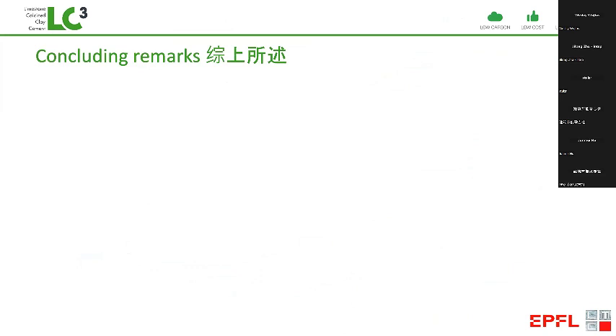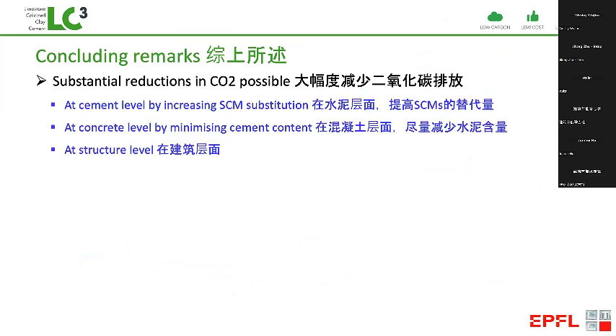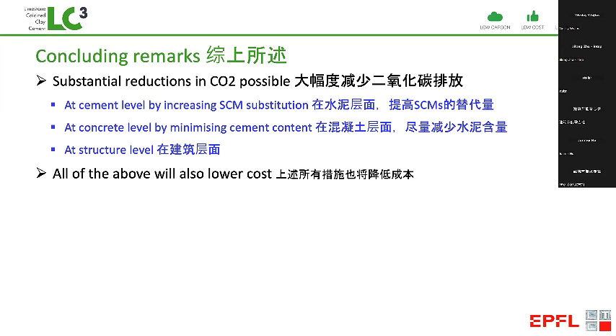So to conclude, I hope I've managed to convince you that substantial reductions in CO2 associated with cement-based materials are possible. We must work at the cement level by increasing the substitution of SCMs. We must work at the concrete level by minimizing cement contents. And we must also work at the structural level, where systematically we see over-design on the level of about 20% or so, and therefore that represents another possible source of saving. All of these will actually lower cost, which is very good news.